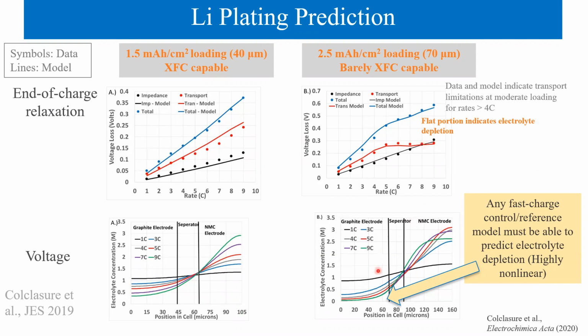Extreme electrolyte concentration results in very sluggish lithium transport and poor electrode utilization. For low loading cell, there is enough electrolyte diffusion to prevent electrolyte depletion in the anode phase even at 9C. However, for the moderate loading cell, electrolyte depletion within the anode and high salt concentration within the cathode occurs for charging rate higher than 4C. Thus, at rates higher than 4C, insufficient electrolyte transport results in severe transport losses and non-uniform electrode utilization for moderate loading cells.